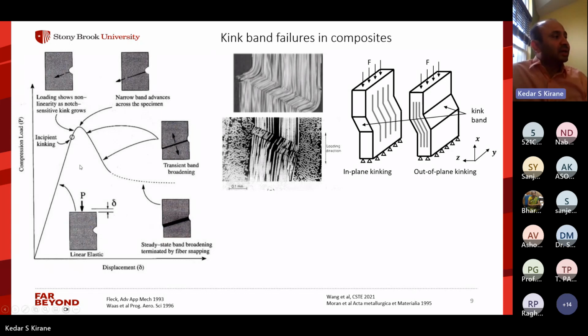And the key characteristic is that when the kink band happens at peak load, the load drops, and then the load actually becomes constant at some non-zero value. So it never goes fully to zero like in tension. When complete failure occurs under tension, the load goes fully to zero. But under compression, it doesn't. And this is called the residual strength. It's often like a plateau, and it represents basically the frictional sliding which occurs in the kink band. And that's a quasi-plastic type behavior. Of course, eventually it will fully break, but it is a very long plateau.